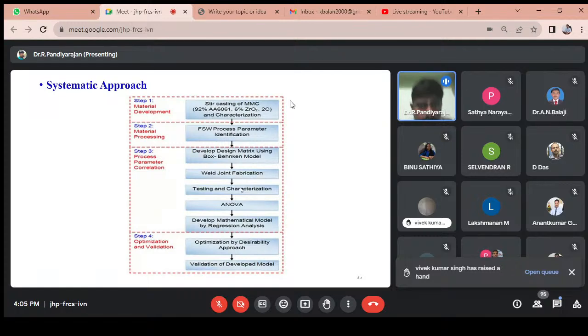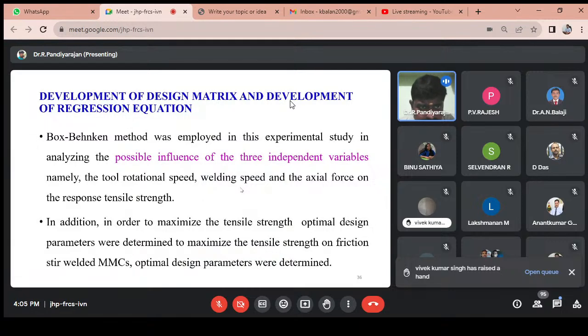followed by the friction stir welding process parameter identification and optimization technique. The development of the design matrix uses the Box-Behnken method. We have to use 3 levels and 3 factors: tool rotational speed, welding speed and axial force, each at 3 levels. In addition, the objective is to maximize the tensile strength. The optimal design parameters were determined to maximize the tensile strength of friction stir welded metal matrix composites. The optimum design parameters were determined using the desirability approach.